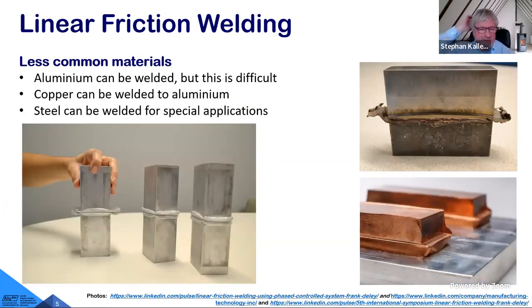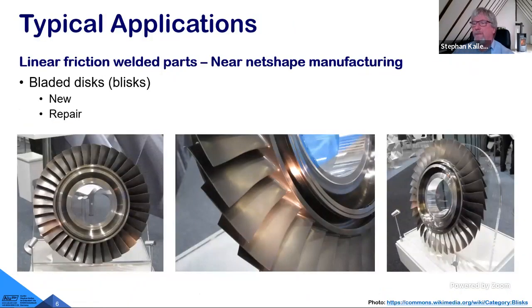The process can also be used for aluminium. In the case of titanium, you have a very low heat conductivity, so the heat really stays in the area that we want to process. In the case of aluminium, it's more difficult because the heat is being sucked into the workpiece. So you have to have really clever parameters, and you get a wide flash, as you can see here on the left-hand side. It is possible to weld dissimilar materials, for example, welding copper to aluminium. And it is certainly possible to weld steel, even in the automotive industry.